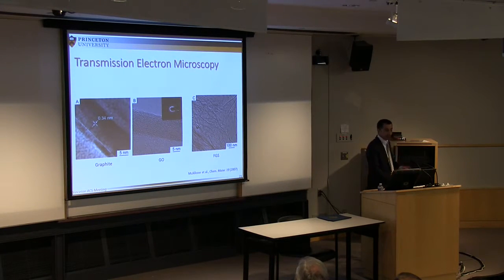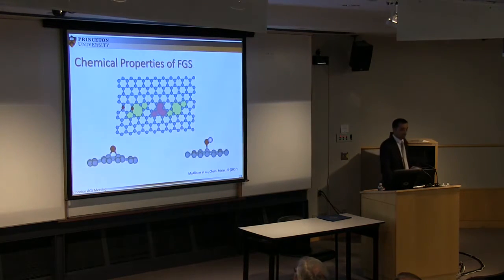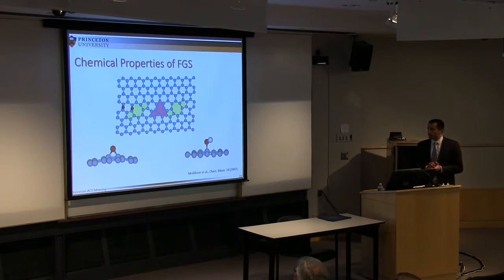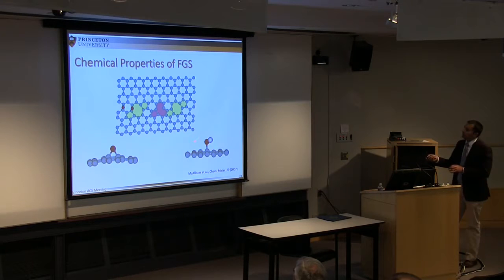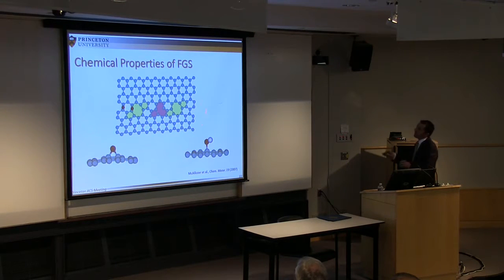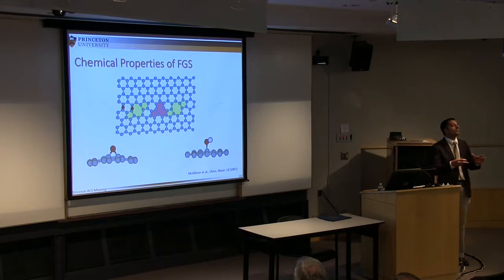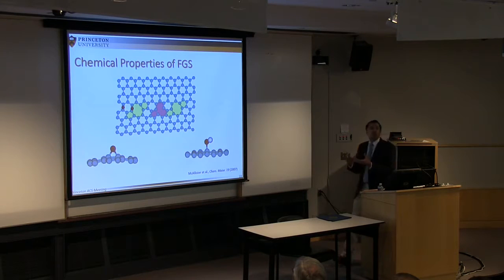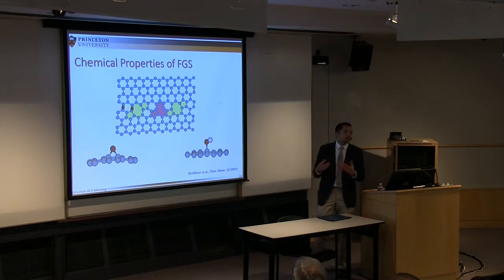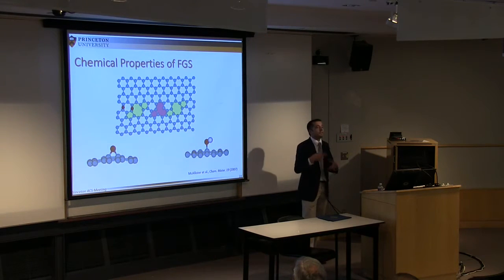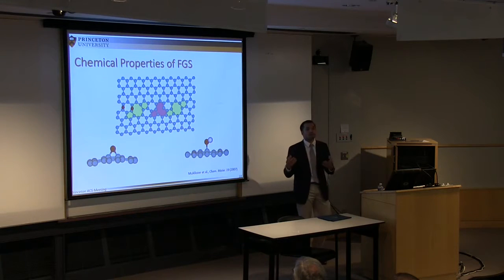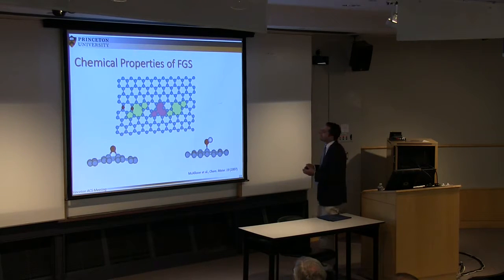But we'll see that those are not necessarily bad for us, because the presence of functional groups in the basal plane, such as epoxy or hydroxyls, or at the edges, carboxylic acid groups, actually help you if you want to do chemistry with them. So if you want to, say, embed them in a polymer matrix, you may have a chance of having a better compatibility than using pristine graphene, defect-free graphene.